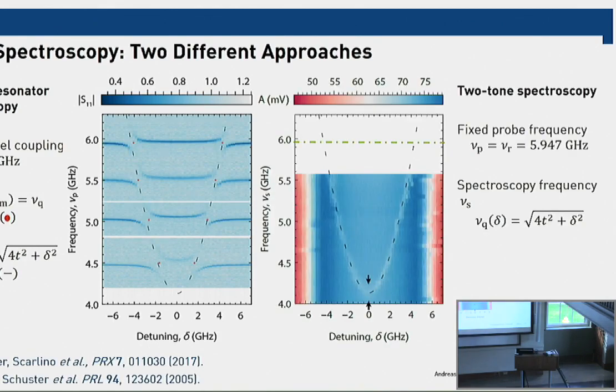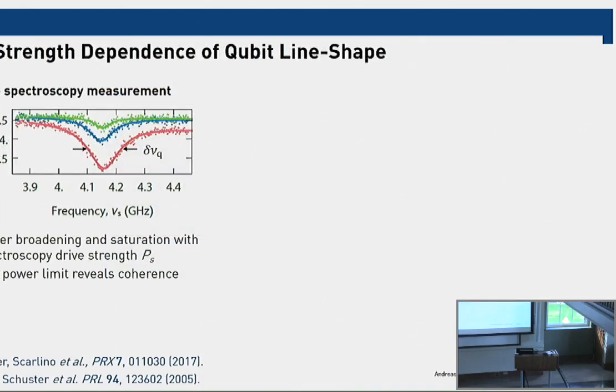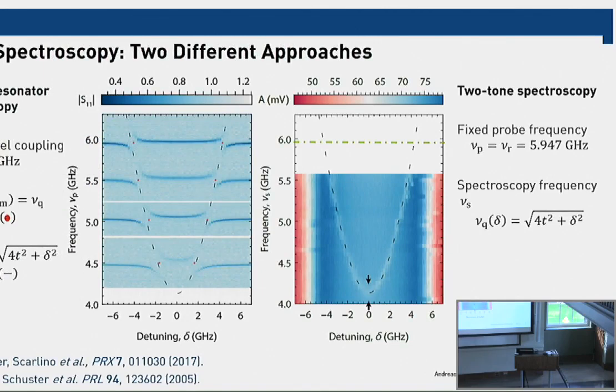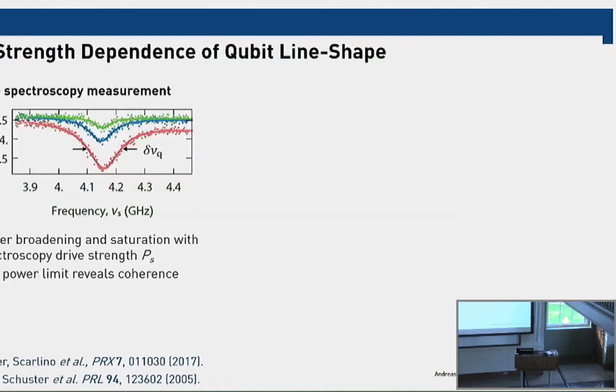So you could do that for spectroscopy, and then you can also do the thing that David Schuster did as one of his first papers at Yale, to use a two-tone spectroscopy to measure how the resonance frequency of the resonator changes when you spectroscopically excite the quantum dot from the ground state to the excited state. And in this type of measurement, you can also extract the quantum dot spectrum spectroscopically, and then measure the quantum dot line width in this spectroscopic way when it's detuned from the resonator itself. And when you see that you have a line width that is reasonable, that tells you that you can probably do time-resolved measurements and maybe spectroscopy.